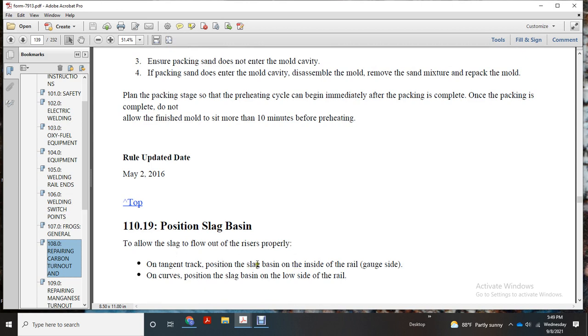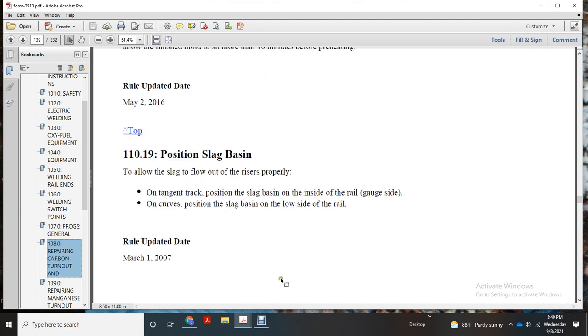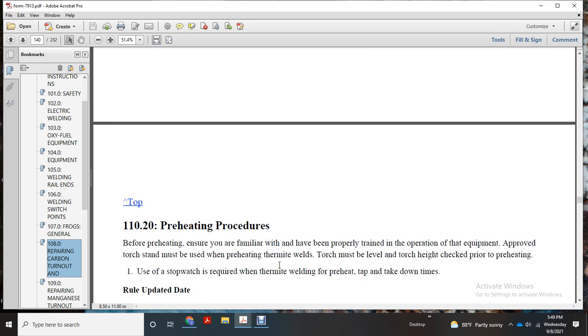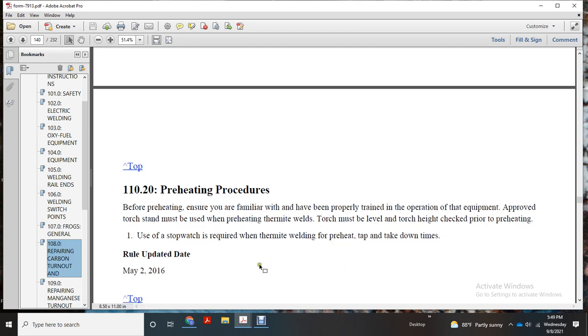On a curved track, position the slag basin inside of the rail with the gauge side, and on uncurved track position the slag basin on the low side of the rail. Preheating procedure. Before preheating, ensure that you are familiar with it and have been properly trained in operating the equipment. An approved torch stand must be used for preheating of thermite welds. The torch must be level, and the torch height checked prior to preheating. Use the stopwatch required with thermite welding for preheat, tap, and other times.